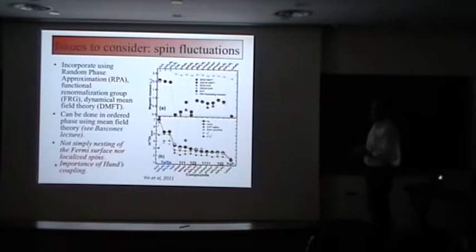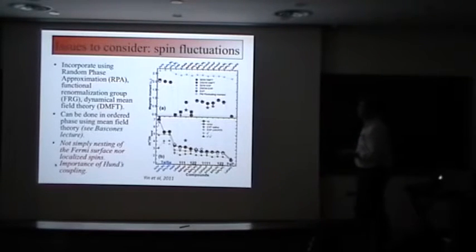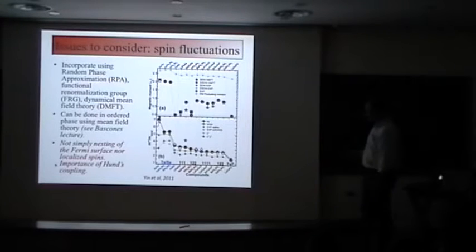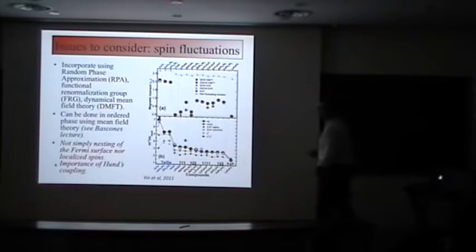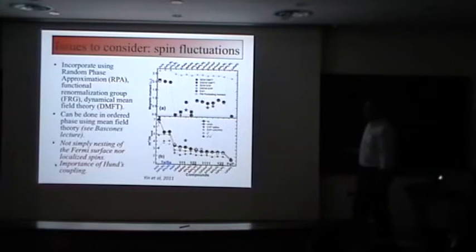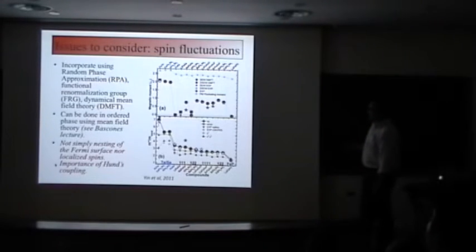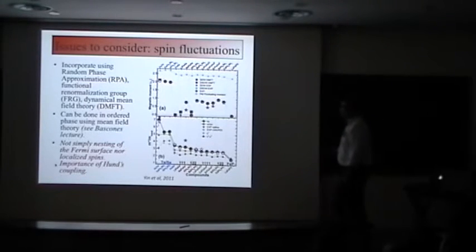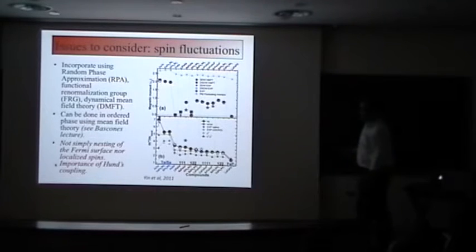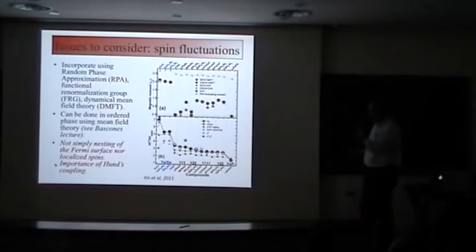And a lot of work has been done in dynamical mean field theory, and this is a snapshot of lots of results from DMFT from Devereaux' group, which, by including the dynamic fluctuations in at least the DMFT-like model, one can get values of the moments which are much lower than what you would get from LDA alone, and correspondingly one gets values of the effective mass.